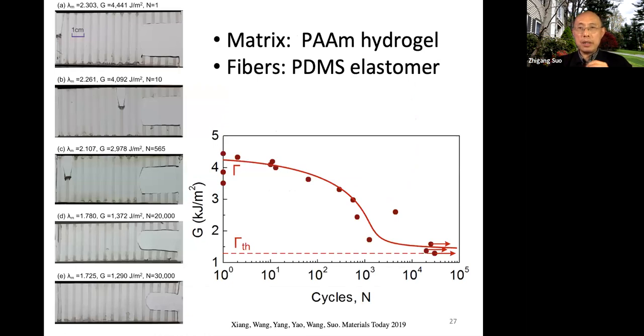And we demonstrate, this is another material with a similar principle: for the matrix we use a hydrogel, and for the fiber we use PDMS, and we measure the cyclic loading. This is kilojoule per meter squared, and this is the number of cycles. If we do monotonic loading, in the first cycle you break; this material has a toughness of 4 kilojoule per meter squared. Very tough material, like natural rubber, right? However, when we do cyclic loading, the student was only willing to do more than 10,000 cycles. So we say this is a threshold. It's more than 1,000 joule per meter squared, just by this mechanism.